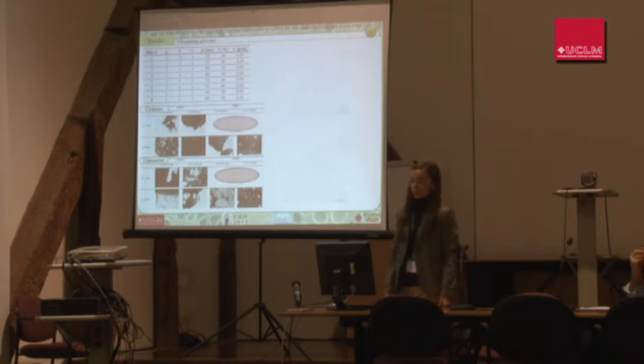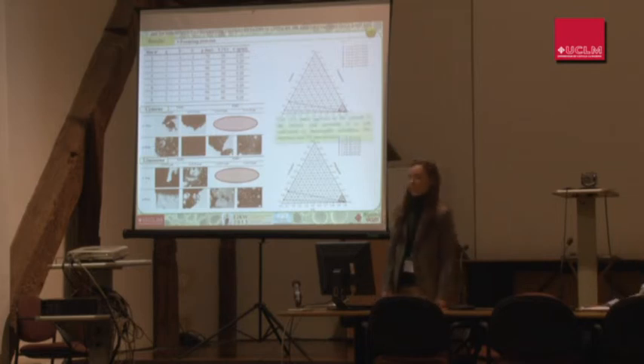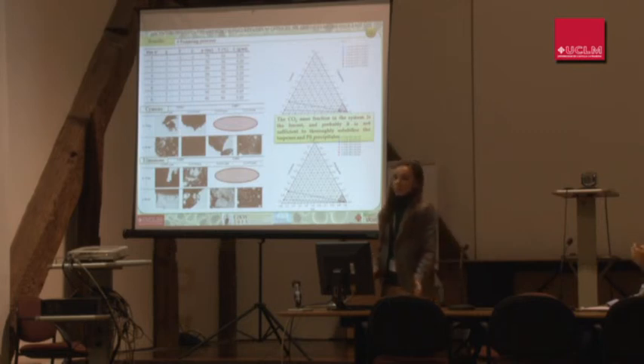Independently of the solvent used, we can observe that at 70 bar and 40 Celsius degrees, no foam was obtained. This is because if we study the ternary system, the carbon dioxide mass fraction is the lowest, so probably it isn't enough to solubilize all the terpene oil and to achieve a dry foam. For this reason, we obtained just a solution.